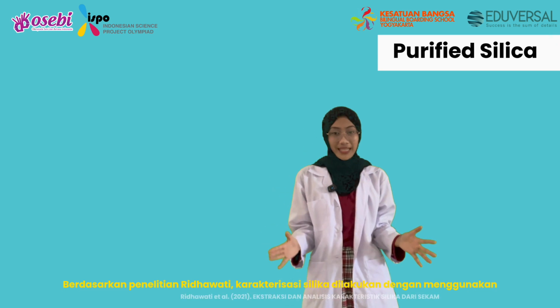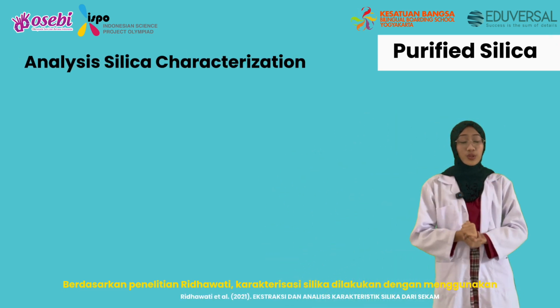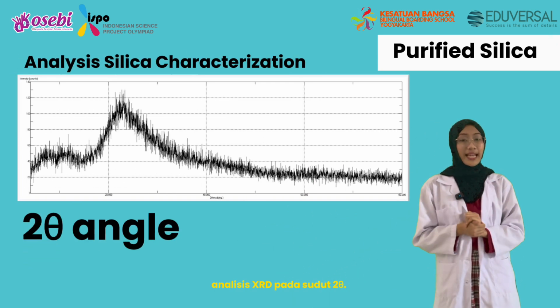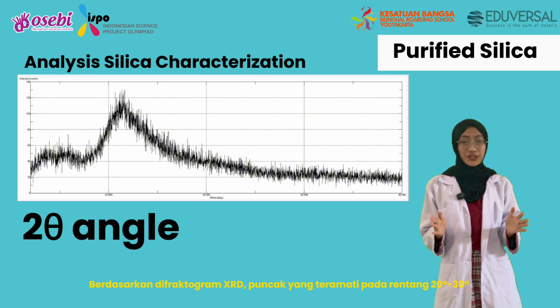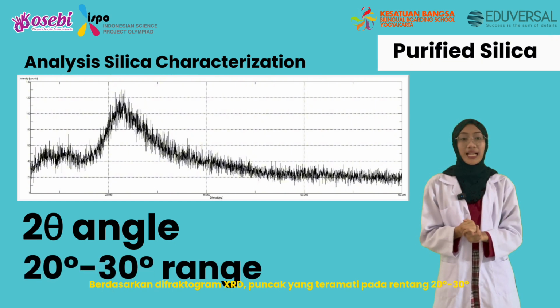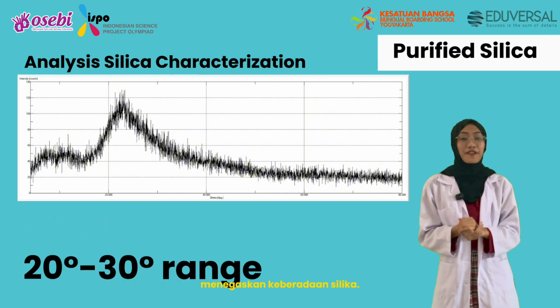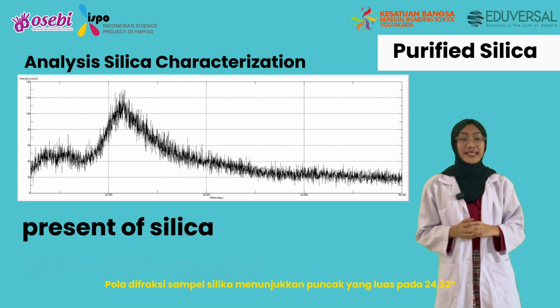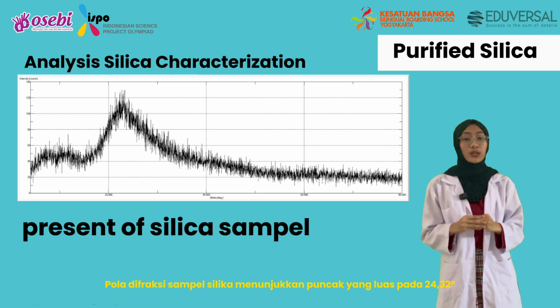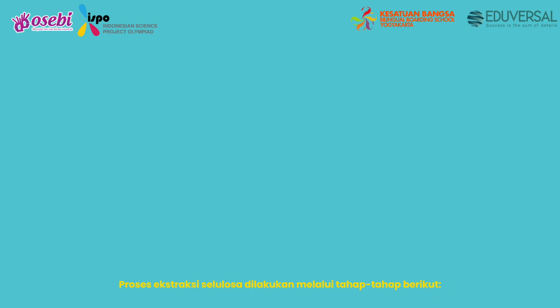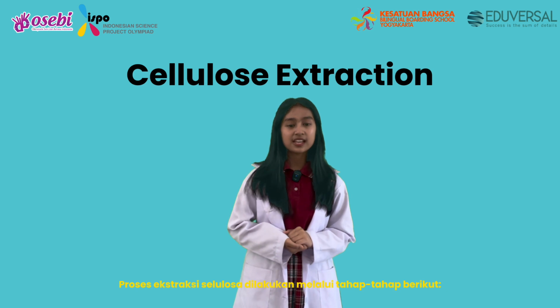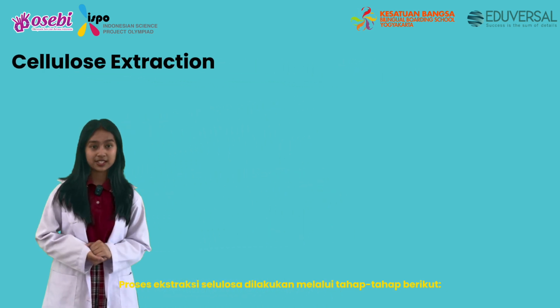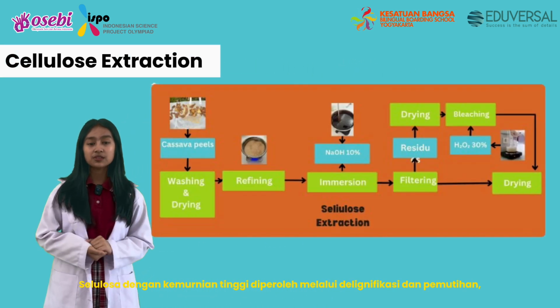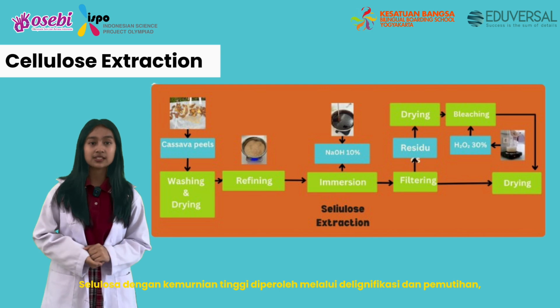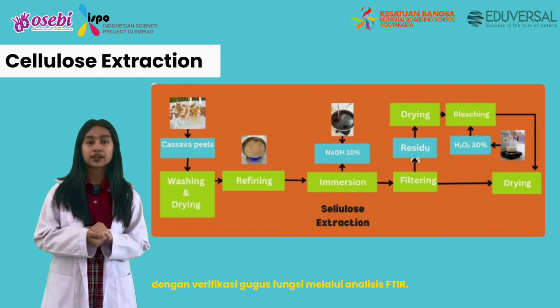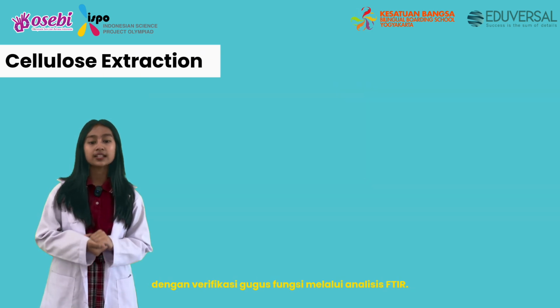Based on research by Ridawati, silica characterization is conducted using XRD analysis at 2 theta angle. According to the XRD diffractogram, the observed peak with a 20° until 30° range confirm the presence of silica. The diffraction pattern of the silica sample exhibit a broad peak at 24.32°. The cellulose extractions process is conducted through the following stages. High purity of cellulose is obtained through delignifications and bleaching, with functional group verification via FTIR analysis.